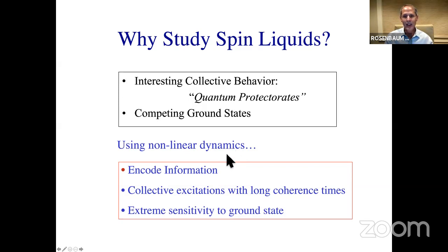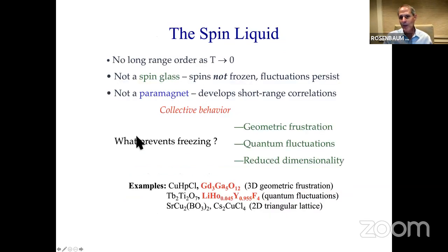By driving the system nonlinearly, we're able to encode information. We have collective excitations that can have coherence times which are tens of seconds. And there's extreme sensitivity to what the ground state is. So what do I mean by a spin liquid? I'm going to use it in the sense that there's no long range order as the temperature goes to 0. The spins are not frozen. The fluctuations persist. And in fact, those fluctuations are quantum in the case of lithium holmium yttrium tetrafluoride.